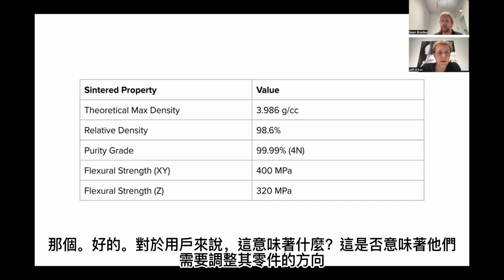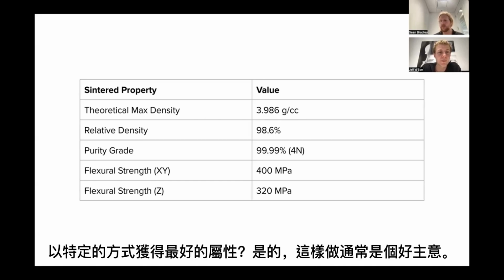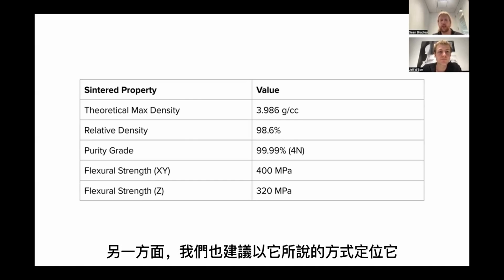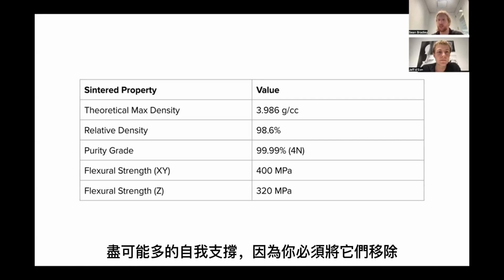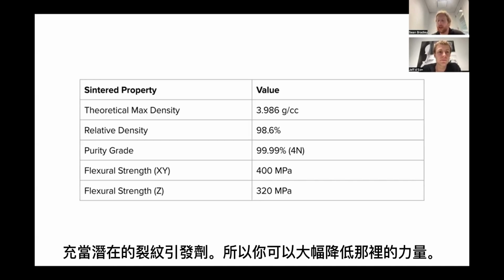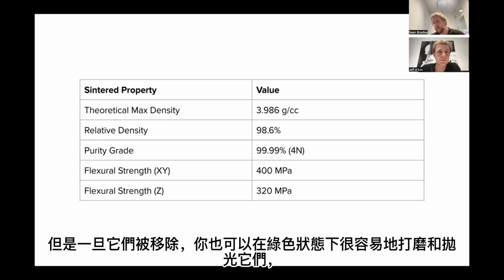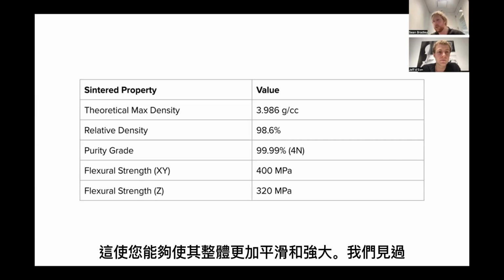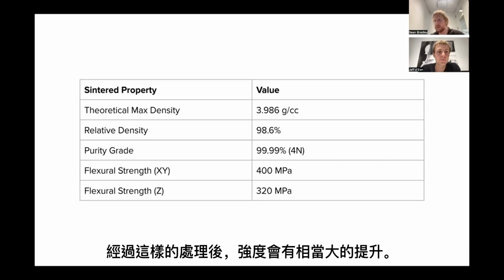Okay, and for a user, what does this mean? Does this mean that they need to orient their parts in a specific way to get the best properties out? Yeah, it's generally a good idea to do that. The other side of that being that we would also recommend orienting it in such a way that it's as much self-supporting as possible. Supports, because you're going to have to remove them, will act as potential crack initiators, so you can substantially decrease your strength there. But once they're removed, you can also sand and polish them off pretty easily in green state, which gives you an ability to make it much smoother and much stronger overall. We've seen a fairly substantial increase in strength when it's been processed like that.